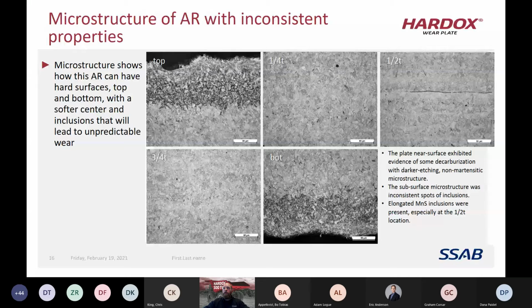And then if you look at the picture to the far right, what we call half T, or half the thickness, you can actually see a void, or actually it's an elongated manganese sulfide inclusion, right at the center of that plate. And so you would definitely see a much different wear property through the center of that plate than you would at the top and bottom surfaces of that plate.